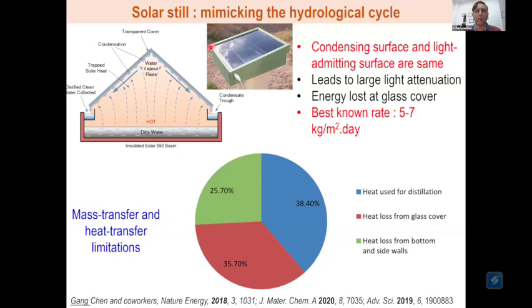With civilization. But then the problem is, if you look at it from a very wholesome picture, you see that the light admitting surface, which is the glass surface on the top, is exactly the same surface on which the water vapor actually condenses. So in the top surface, this is where the sunlight penetrates, ending up heating the water. And once the water evaporates and forms water vapor, the condensation starts to happen on the same surface. This means that this is going to be a self-limiting process, because once you start forming water drops, you're going to attenuate the light intensity which is going down, and therefore the heating and the water vapor production starts to naturally decrease. So this is a kind of vicious cycle or a self-limiting process.